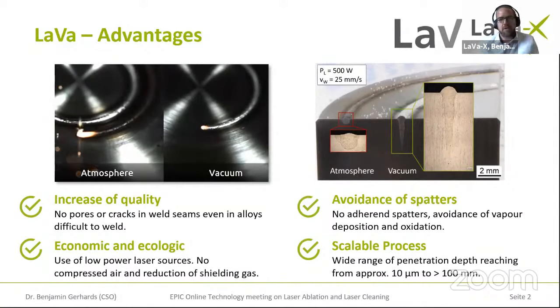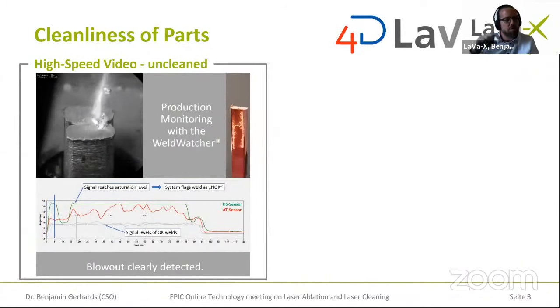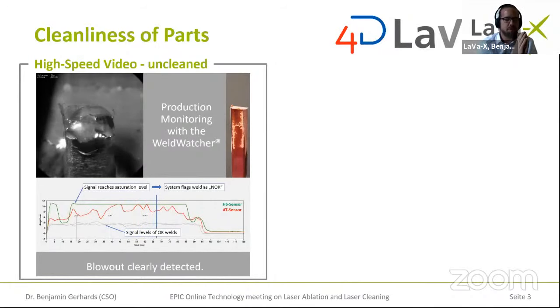So in the case of welding those copper hairpins, for example, we have a video that I want to show you that was made by our cooperation partner 4D, and it shows when the laser beam's trajectory goes over the gap, you will see a large weld pool ejection like this. And this is due to the rest of insulating material that is between those two pins that are welded. And you can see not only that we have spatters that occur that might lead to short circuits somewhere in the stator, but also we will have significant pores that are in the molten pool and that will be trapped in the material and therefore reduce the electrical conductivity.